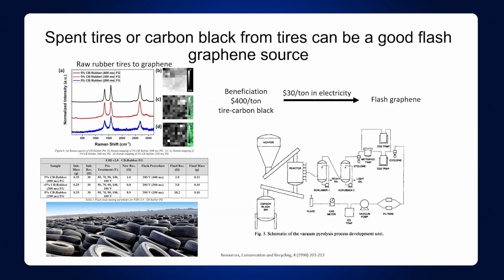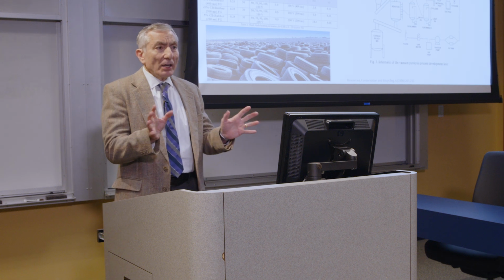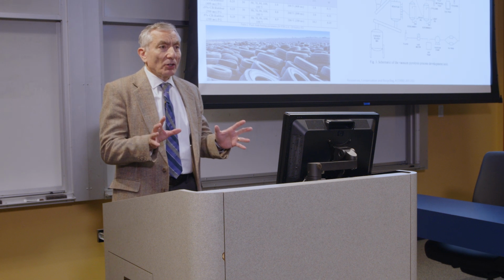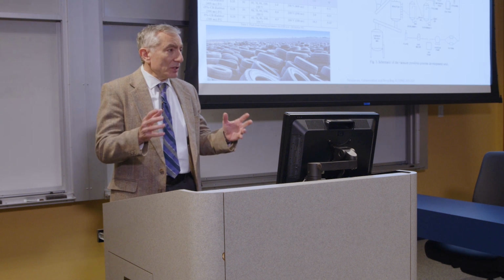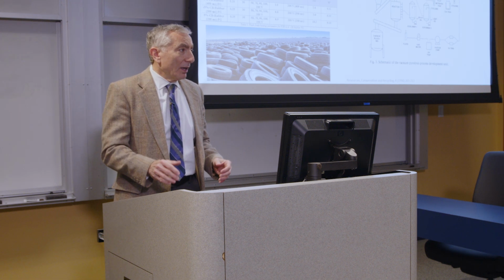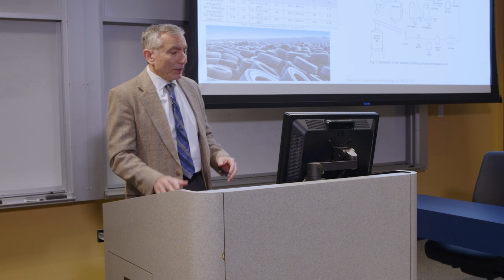And you can take that carbon black and you put it in the rubber, and if that were not in the rubber, the tire would stretch too much. This really toughens the tire, that carbon black. It can be 30, even 40% of the rubber tire by weight. I don't know if you've ever picked up a new tire. Your hands are going to be black. And that's the carbon black that's all over the surface, because it's all inside it too. And that's why new tires will always make your hands black.